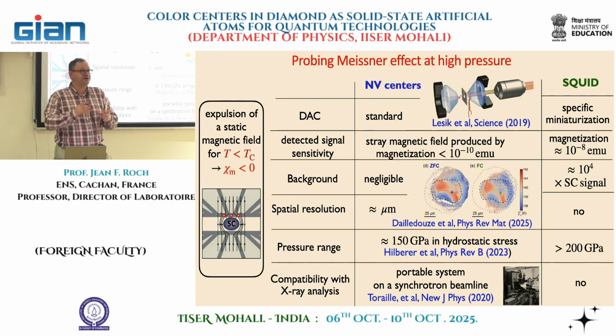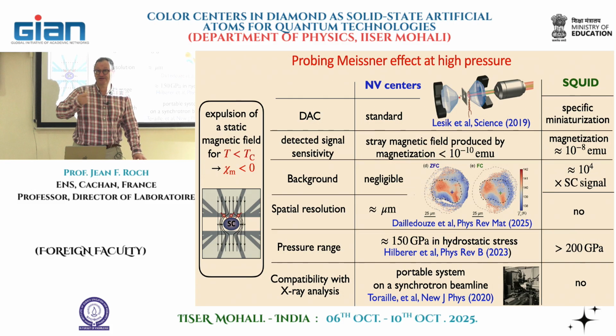So we observed the alpha to epsilon pressure-induced transition of iron on a synchrotron beamline. So we could do, at the same time, the measurement by X-ray diffraction of the evolution of the crystal from the alpha structure to the epsilon structure, and measure simultaneously the evolution of the magnetic response.